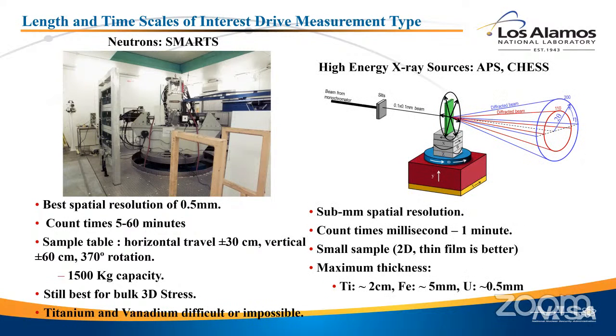X-rays, on the other hand, at the APS and CHESS, are advancing in terms of flux and brilliance at a rate that's unbelievable, and I won't go into the details, but it allows you to do things that neutrons just can't. You can get sub-millimeter, micron type spatial resolution with X-ray beams. You can get sub-second resolution. There are places like the Linac Coherent Light Source that use X-ray lasers to get femtosecond or tens of femtosecond time resolution. So if you're looking at something like an exploding component, you can get an image in tens of femtoseconds with those types of X-ray sources.